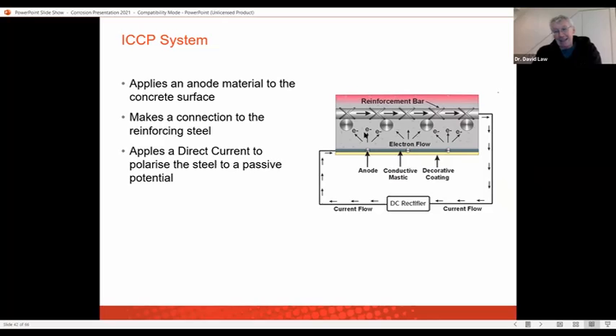And it's this secondary effect where we think we could get this residual protection and the restoration of passivity, because we've regenerated hydroxyls, we've moved chlorides away, so we can repassivate our steel bar. And if our steel bar is repassivated, then it will be a period of time before corrosion is reinitiated. And the idea behind the hybrid is if you've got some zinc, it will then be able to protect it, and you will not lose that passivation now you've got it for an even longer period of time.